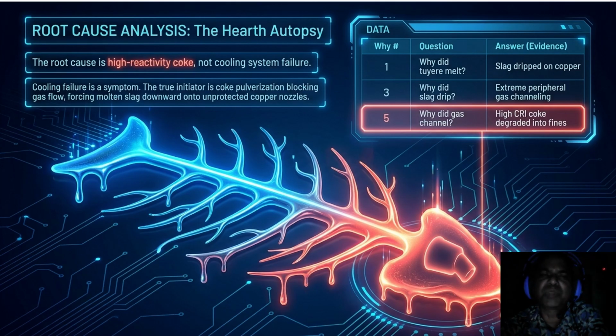Why did the slag drip? Because of extreme peripheral gas channeling. And finally, why did the gas channel? Because the high reactivity coke degraded into fines, blocking the center and forcing the gas to the wall. So the root cause is high reactivity coke, not a cooling system failure. The cooling failure is just the final symptom of the metallurgical breakdown that started days earlier. We have to stop fixing the symptom and start controlling the chemistry of our input. If we don't keep the gas in the center, we will keep burning copper no matter how much water we pump through it.